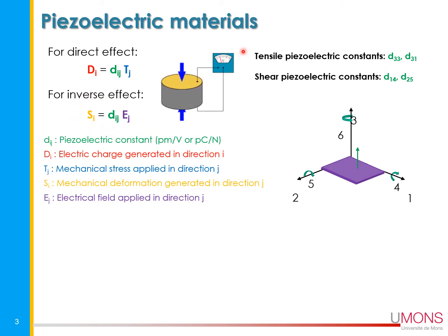And those relationships come from this matrix, which is actually a tensor, depending on the direction in which you apply a constraint, and you are measuring the effect of this constraint. So indeed, in most of the polymers that we will see and we saw before, we have the D33 or D31, which are the most common tensile piezoelectric constants, but for PLA, it's more the shear piezoelectric constants that are involved, and that's why we have to measure the D14 or the D25.